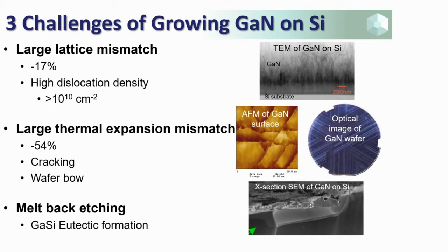And so when you deposit gallium nitride on silicon, the gallium nitride tries to use the silicon atoms in the surface, that arrangement of atoms, as a template. And it tries to put down the gallium nitride atoms on this silicon template. You have this large lattice mismatch, and it's accommodated by defects called dislocations. And you can see a fuzzy picture of dislocations up the top. So that's one thing, you have to solve that problem, because the dislocations quench the light emission. So the electrons and holes, instead of recombining in the quantum well, combine at the dislocations and don't give out light.